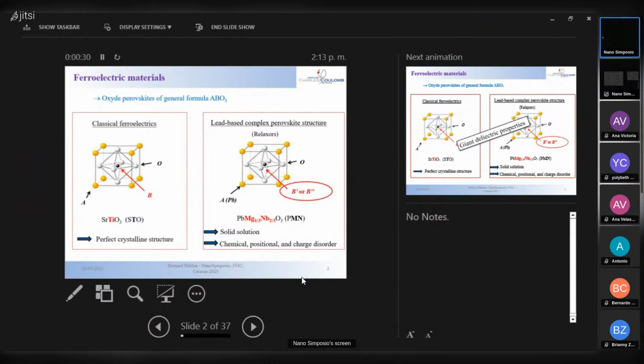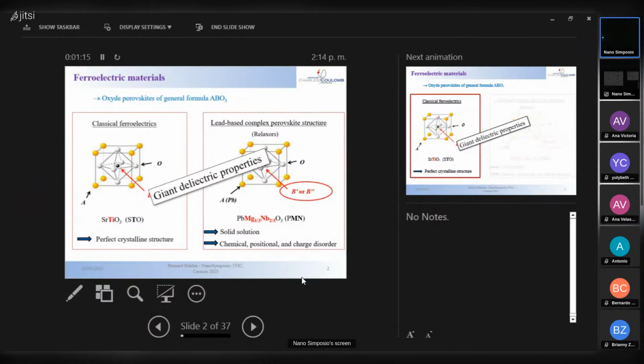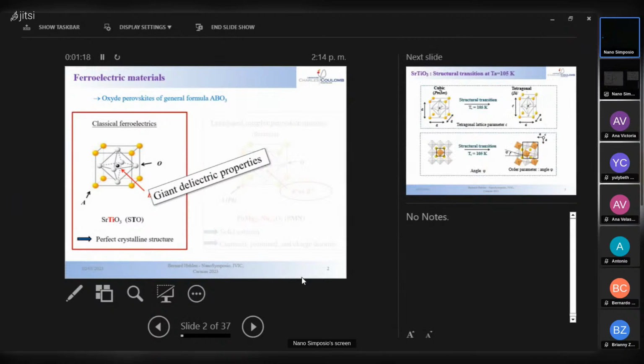You have complex ferroelectrics here, which exhibit exactly the same structure as strontium titanate, but in those systems, the central site, the B site, can be taken by two different atoms, B prime or B second, and this makes what we call a solid solution. For example, in this sample here, the B site is made of magnesium and niobium. This makes solid solutions, and the properties are due to the chemical, positional, and also charge disorder of the system. All of these materials exhibit giant dielectric properties, but today I will focus on strontium titanate, which is the simplest form of this kind of materials.